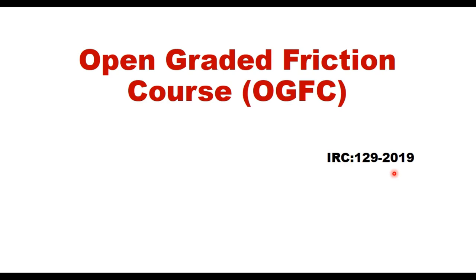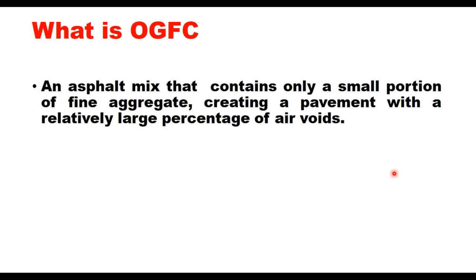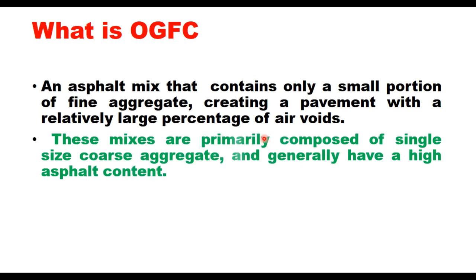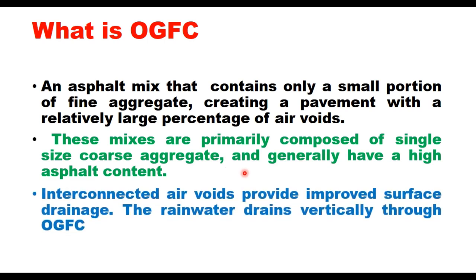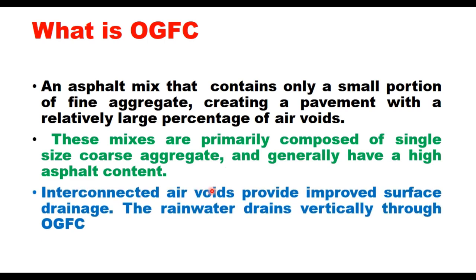OGFC is a thin open-graded asphalt wearing course which has been successfully used in many countries. This is an asphalt mix that contains only a small proportion of fine aggregate, creating a pavement with a relatively large percentage of air voids. These mixes are primarily composed of single-size coarse aggregate and generally have a high asphalt content. These interconnected air voids provide improved surface drainage.